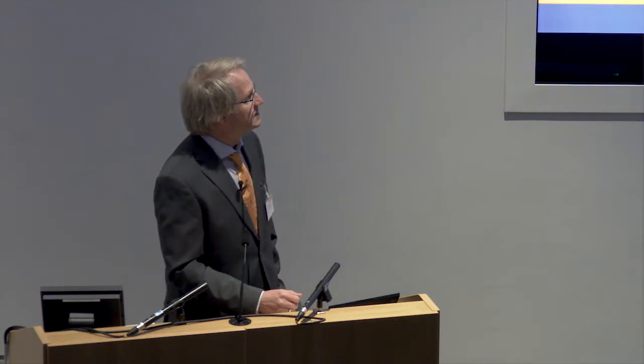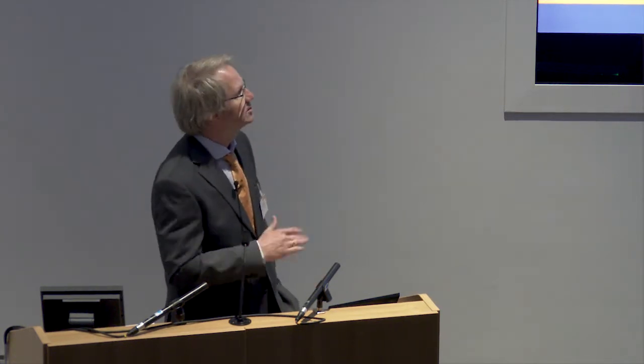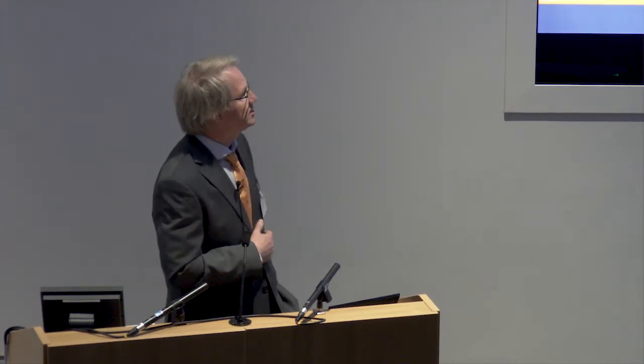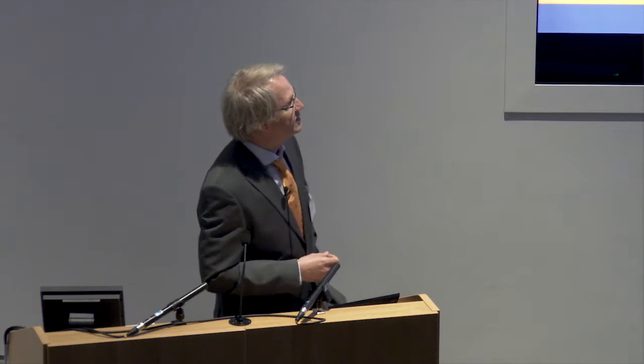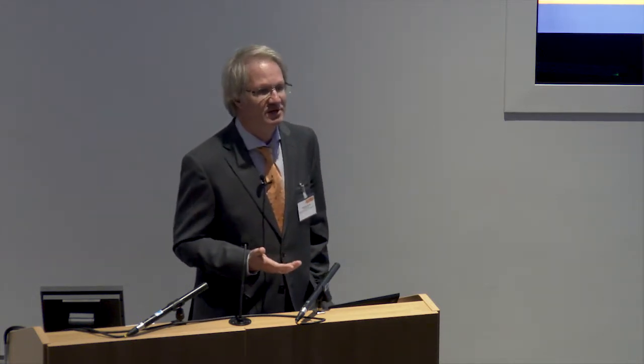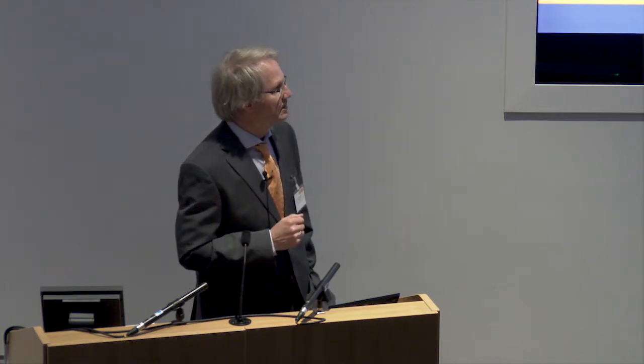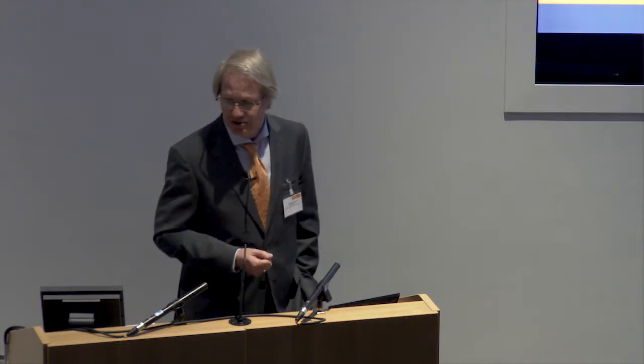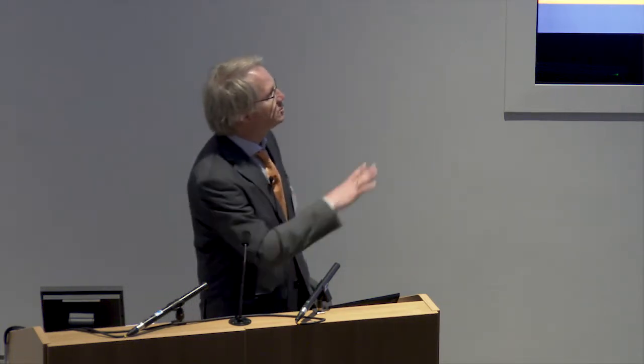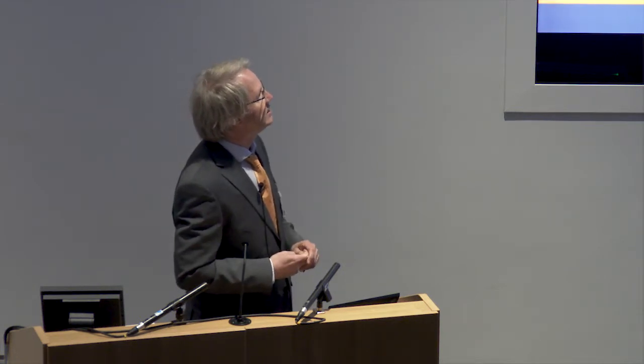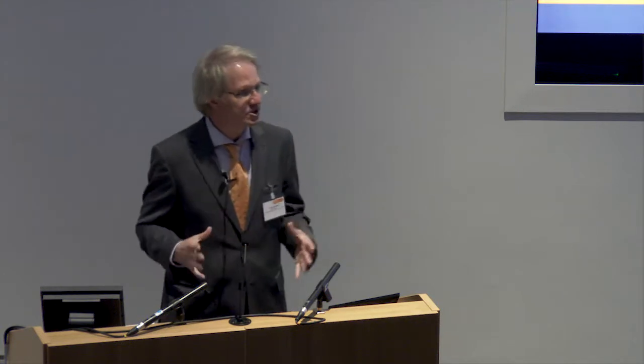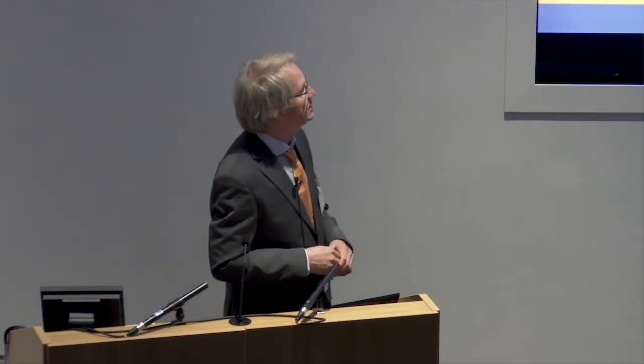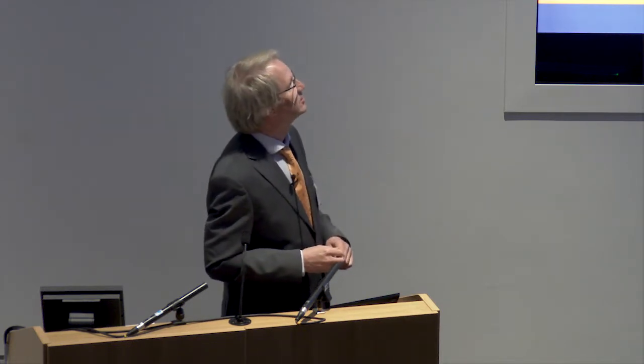What we have learned so far is that these additive manufactured parts sometimes look different. If you use different processes, you may have different geometrical changes, different shapes in the minor millimeter area, but it is a good idea to have a fixture design which is flexible enough to cover these part-to-part deviations. And therefore, for example, the MTC team introduced this blue slider, so that the operator is able to handle the individual part in a proper way. It's not a good idea to design the fixture in a too stiff, inflexible manner, because you will run into problems later on during the processing.